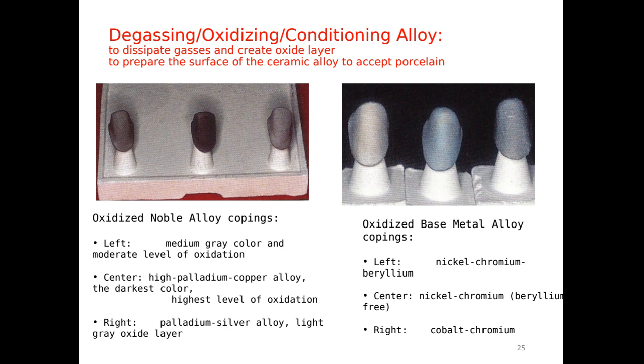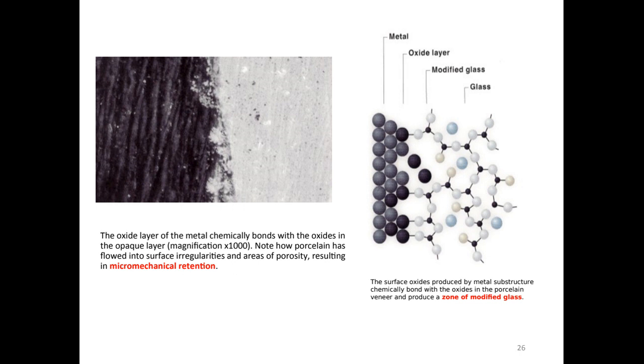On the right picture, for the base metal, starting from the left, that's nickel chromium beryllium. So we see it's a light color. The center is nickel chromium, so it doesn't have beryllium. And then on the right, it's cobalt chromium. So this is how the oxide layer looks under the microscope. And again, this is how the porcelain creates that bonding with the alloy.